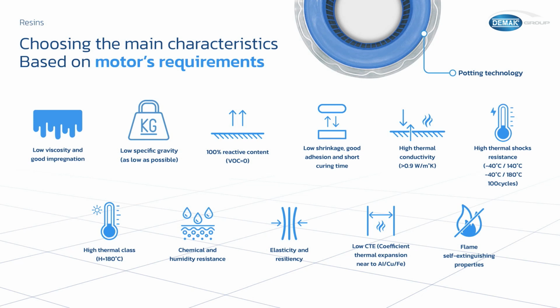So here you see some parameters that we look for: as I say, low viscosity, also the lowest possible specific gravity, important for the car, for example. Totally reactive system, no volatiles inside. Low shrinkage and good adhesion to the part. High thermal conductivity, as I say, in order to dissipate as much as possible the heat developed by the motor.